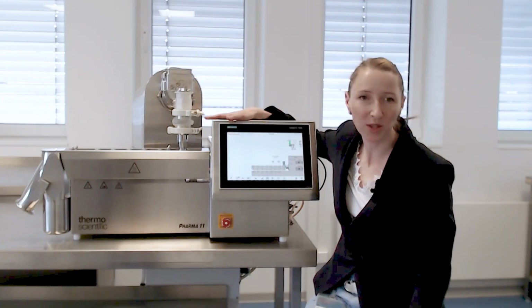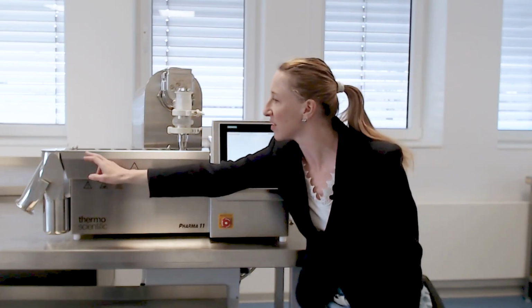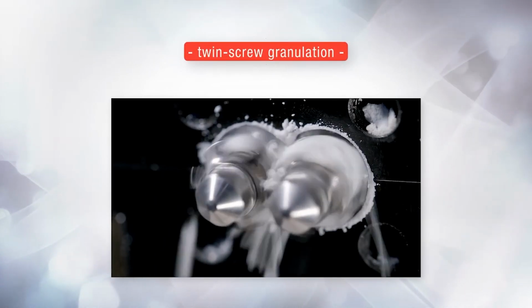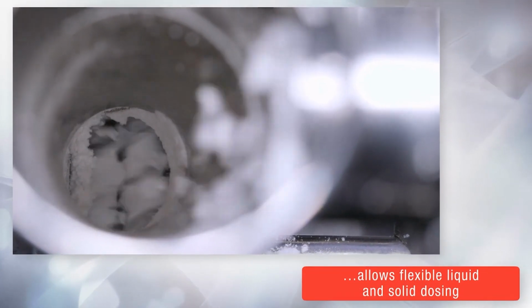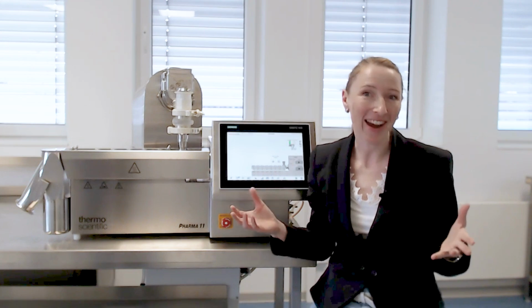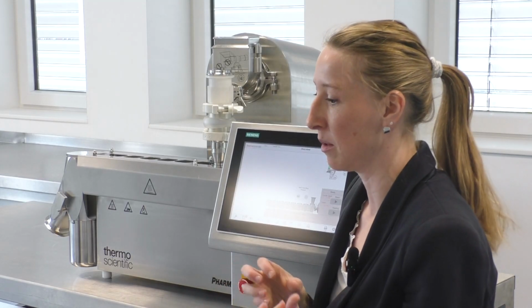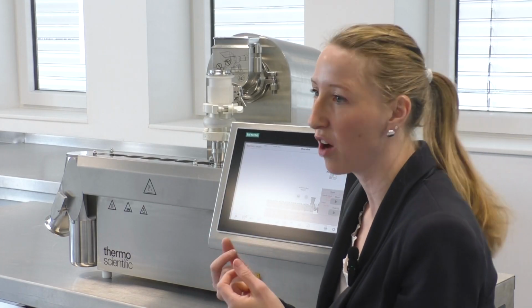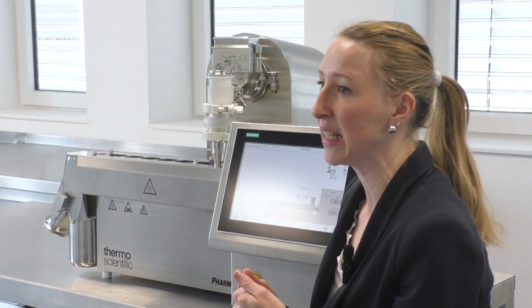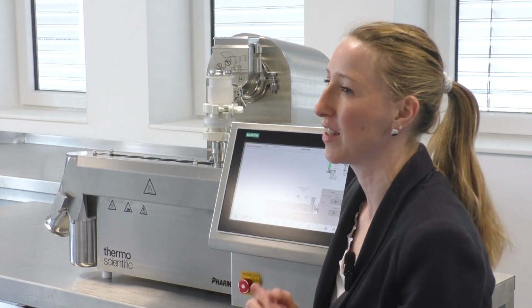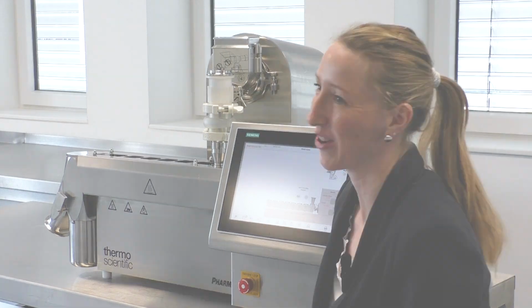Well, you use that twin screw extruder in a granulation mode. So this is what we set up here. You don't use a die at the extrusion system, but it's open, and basically the screws mill down the material. At that point, we asked ourselves, okay, does this work with a pharma grade silica, which is basically not a mill, right? It works very well because the silica is rather soft and it breaks down very easily. So we could run it on this twin screw system very nicely.